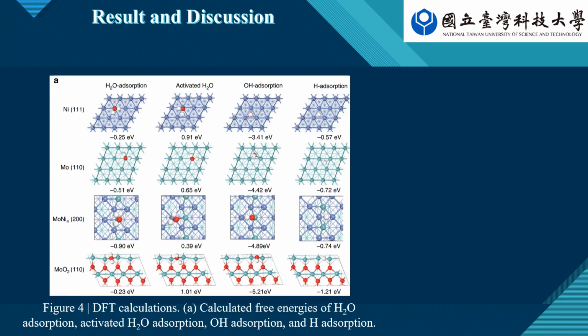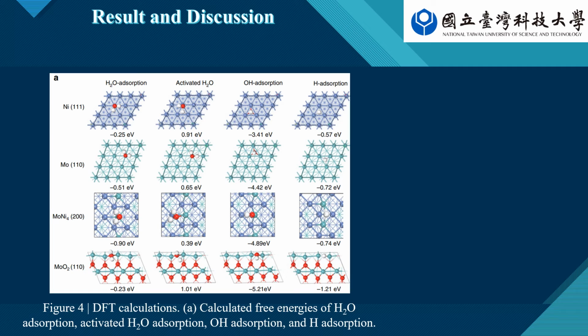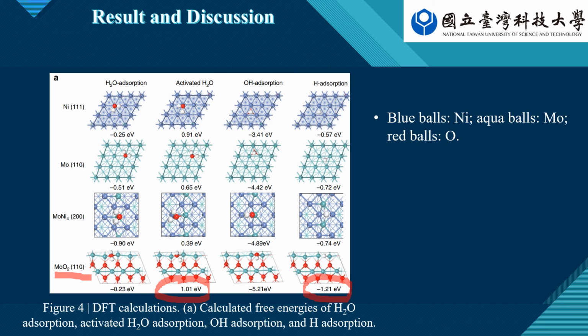In figure 4a, this is the illustration of the molecular bond and calculated free energy, where the blue balls are nickel, the aqua balls are molybdenum, and the red balls are oxygen. Molybdenum dioxide has a large energy barrier for the Volmer step, equal to 1.01 electron volts, and a strong hydrogen adsorption free energy equal to 1.21 electron volts, indicating a very sluggish Volmer step mechanism. Thus, molybdenum dioxide is not a very highly active center for the HER, which agrees well with the experimental result.